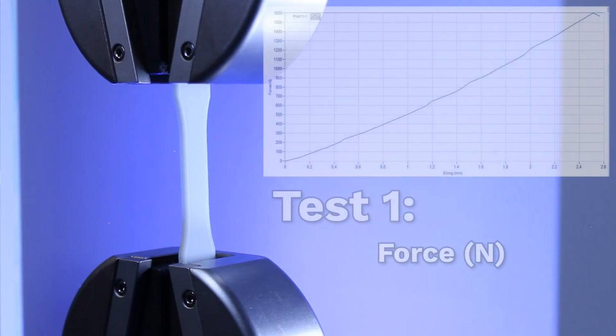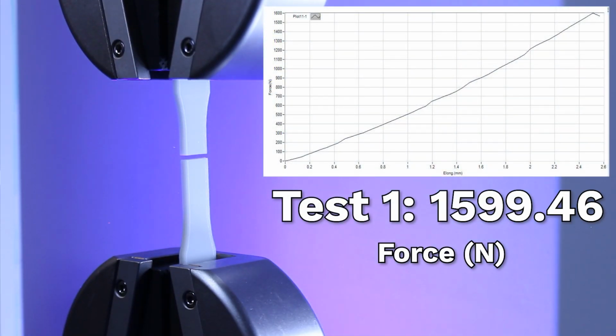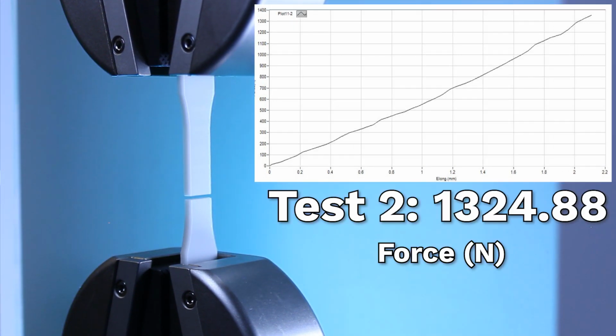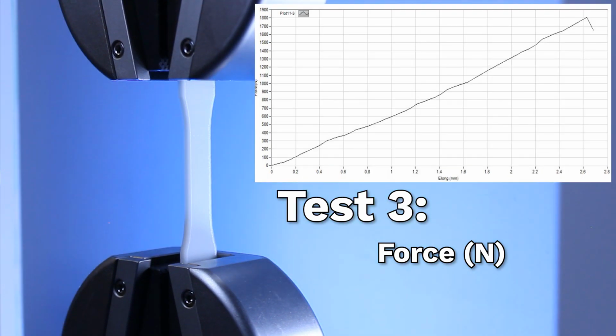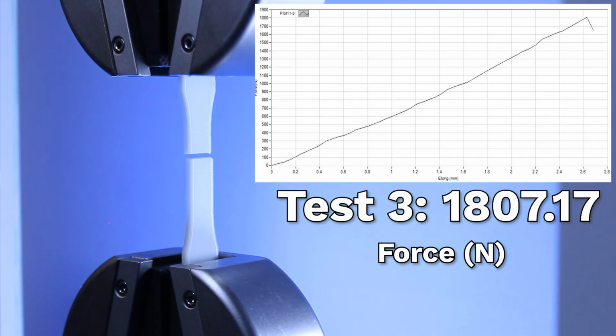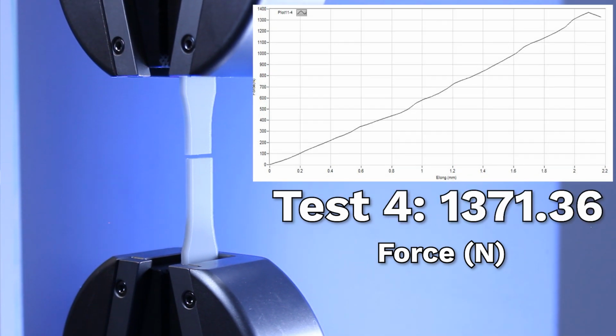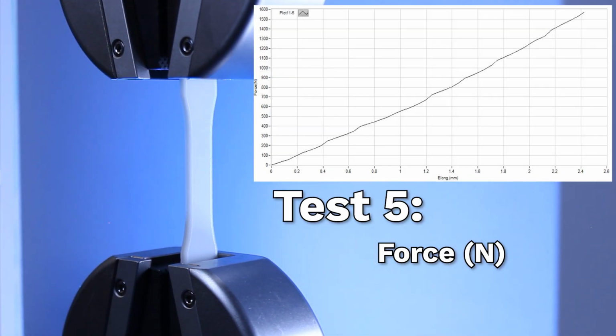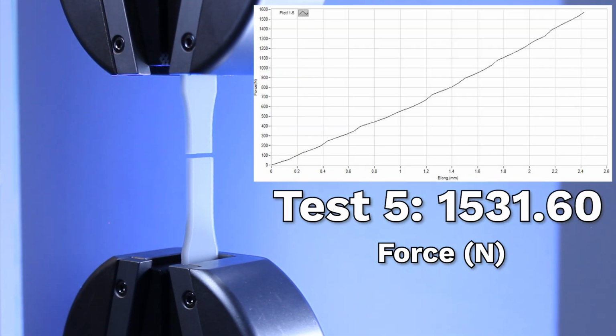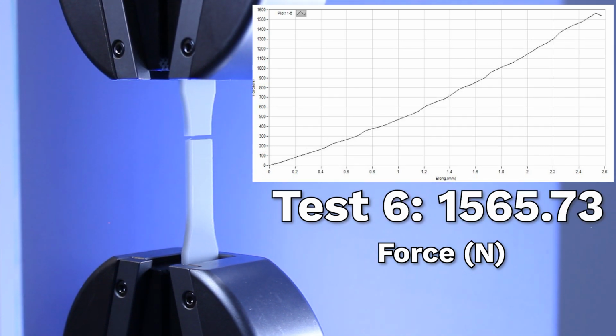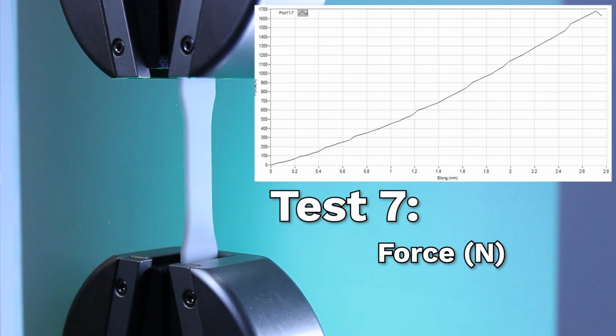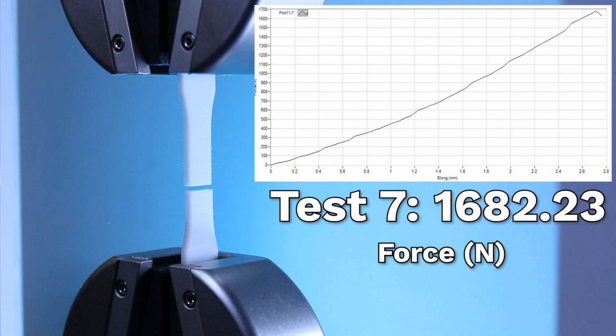Then of course we went ahead and moved on to the gray itself. The first test was, of course, for black, moving into the second test for gray. This was actually kind of interesting. With the gray PLA, we did see more noise, more variability in the results. It still hovered around the 1700 average, but the differences between these different components were pretty radical, even though these were printed on the same machine with the same raw material.